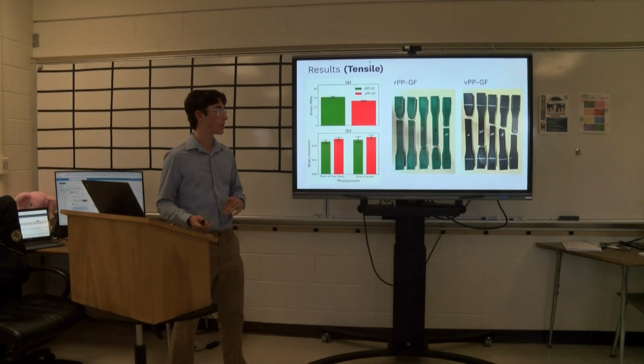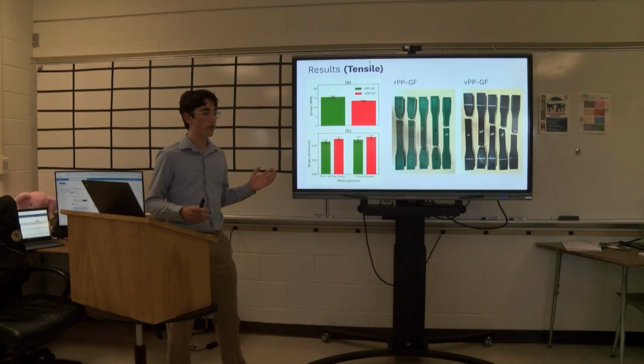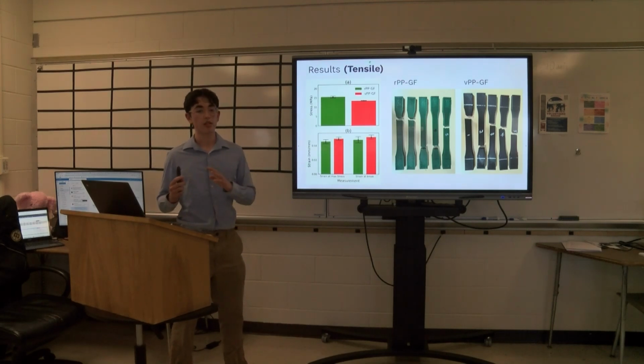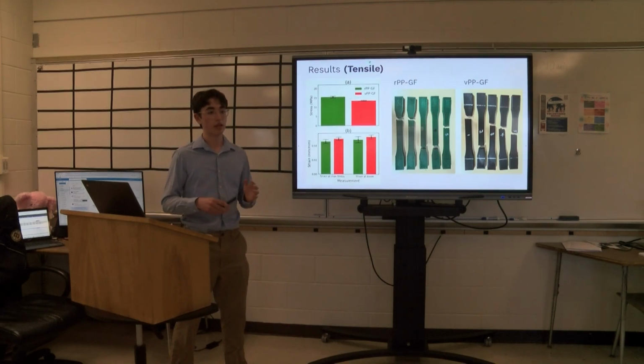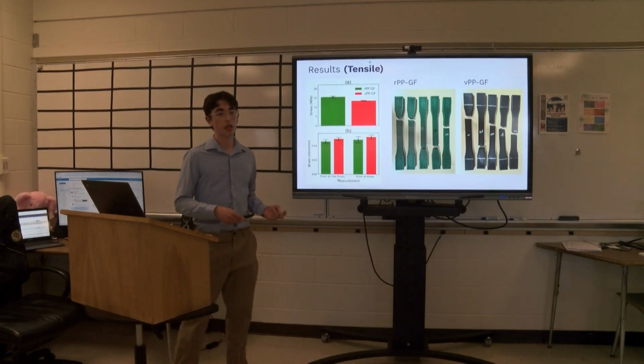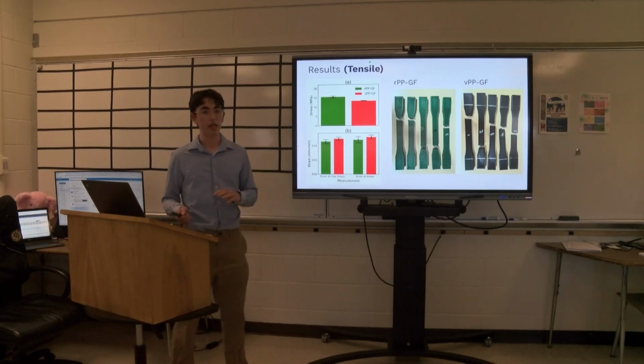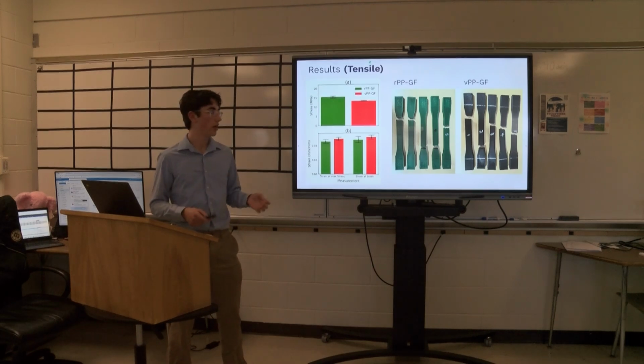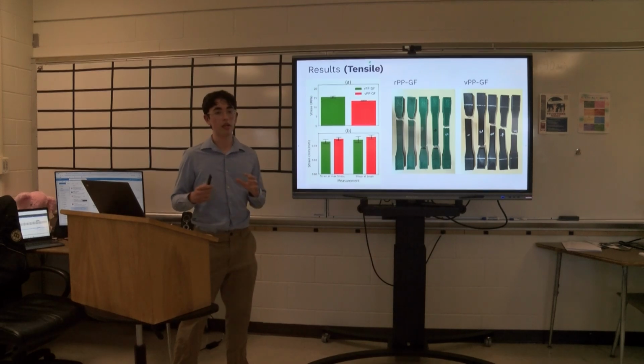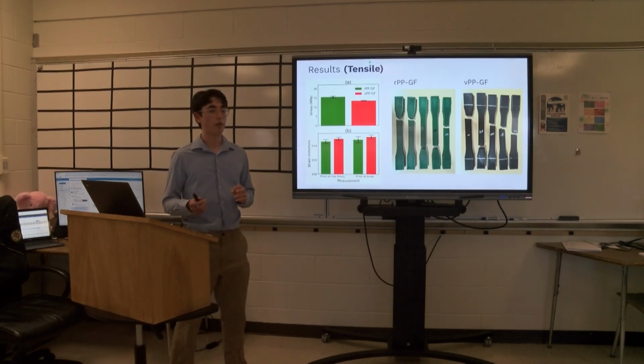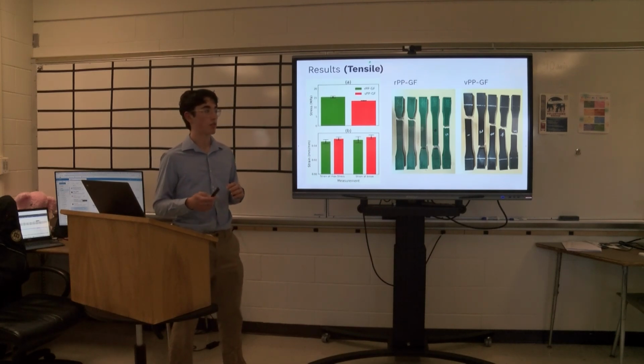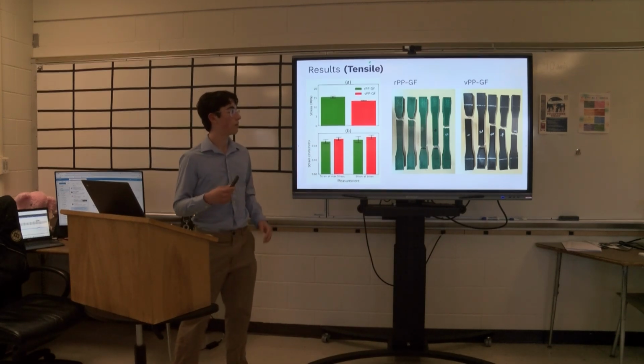Now, moving on to the tensile test, if you look at the figure on the left, figure A compares the max stress, which is sort of like the strength, between the two materials, while figure B compares the strain at max stress and the strain at break. And from these figures, it can be seen that the virgin material can withstand a higher elongation or a higher strain, while the recycled material can withstand a higher stress or higher strength. And this is something quite commonly seen in crystalline materials. You see that the recycled material becomes more brittle and obtains a higher maximum stress. And this is also further exemplified by the figure on the right.